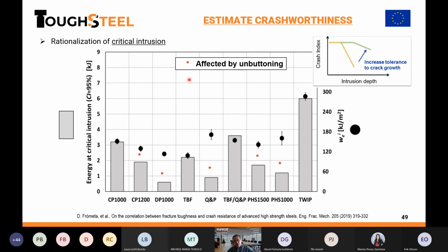We can also use the initiation energy to rationalize critical intrusion. What is critical intrusion? In this plot of the crash index versus intrusion depth, the intrusion is the point where the damage starts, so when the crack starts. If we look at the different specimens, the ones with this point cannot be explained because the crack starts from the spot welds. So the behavior is not because of the material, it's because of the spot weld.